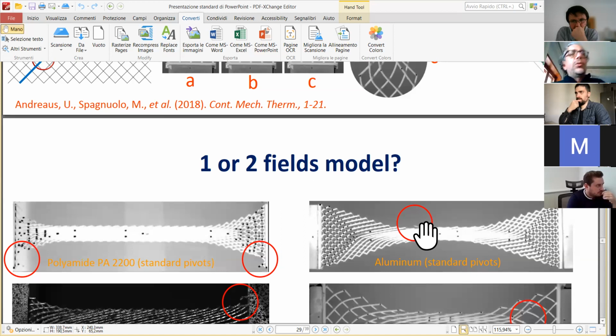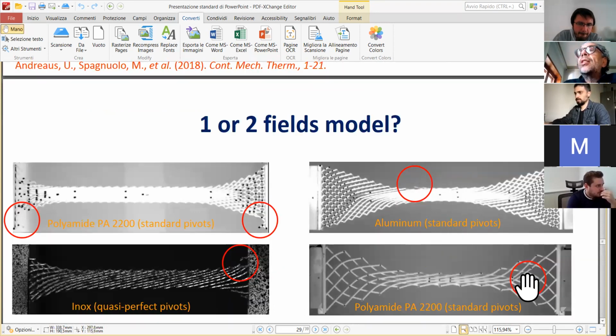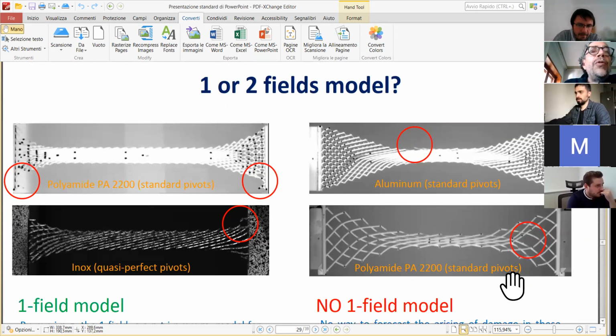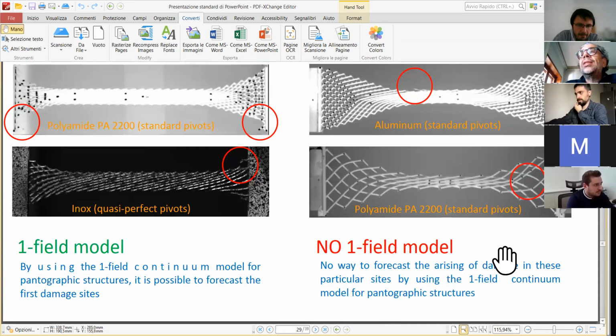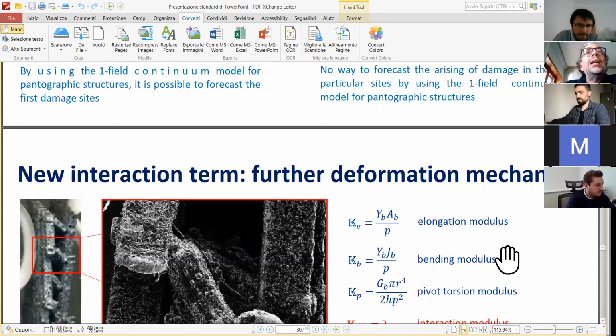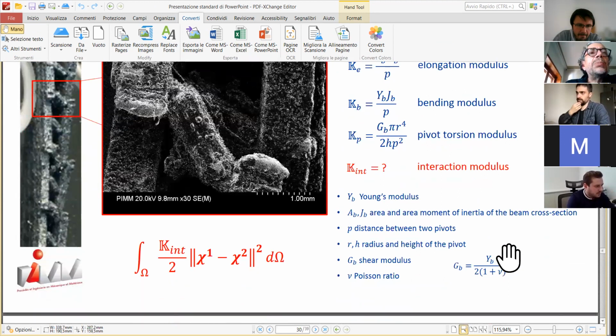So, standard continuum models are not good for describing these systems. We used a second gradient continuum model, so a model where second gradient of displacement appears. Actually, we invented this microstructure for finding this kind of microstructure. Then this phenomenology urged us to develop a two-field model, and using this two-field model, we did manage to describe also this rupture phenomenology.